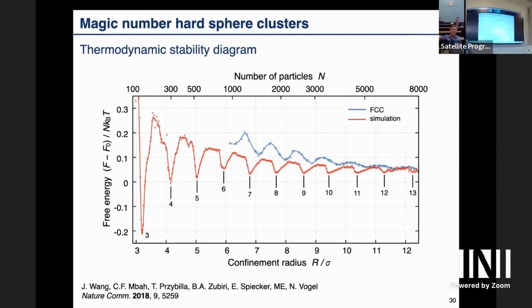And you're saying if you go farther to the right, FCC has to win ultimately? Yes, that's the other thing. Yeah, I didn't say it here. We also compare to FCC clusters. So those we didn't simulate long enough that they actually revert to something else. But FCC is less stable for these, and it does cross somewhere at 10,000, 20,000. Eventually it crosses. It depends on density where exactly it crosses.